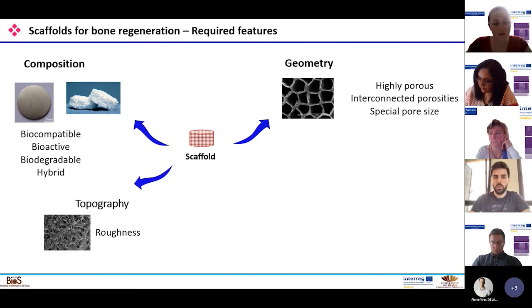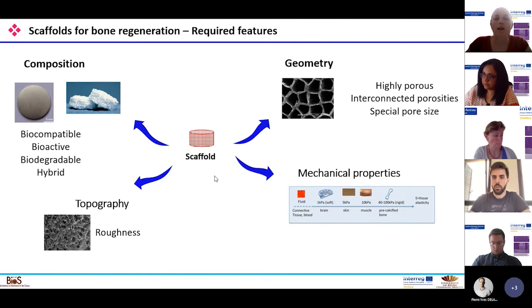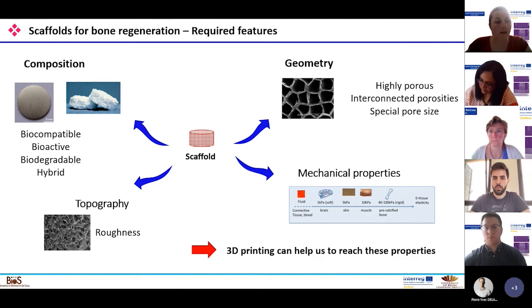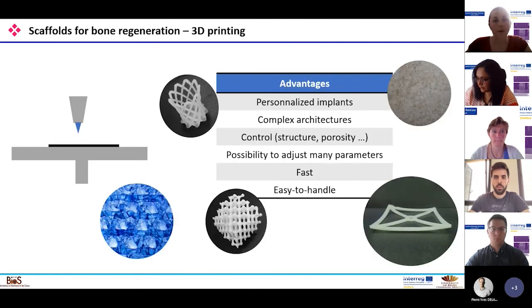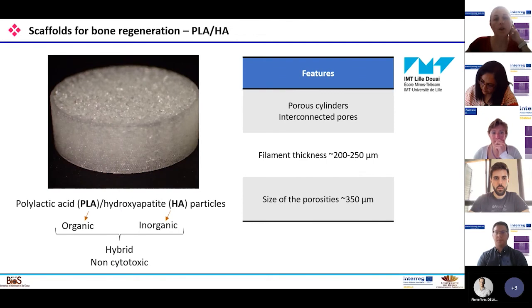Then we have the topography, which is an important parameter for bone regeneration, especially as the roughness of a scaffold can induce or stimulate stem cell differentiation. And then the mechanical properties are also a crucial parameter because they can also induce stem cell fate. And we are trying to develop scaffolds with similar mechanical properties to the bone. And we think that 3D printing can help us to reach all these strict features to design scaffolds for bone regeneration. Indeed, among the main advantages presented here, the control of all the previously required features is possible with 3D printing.